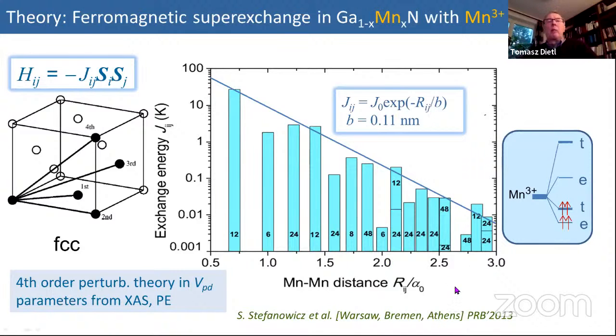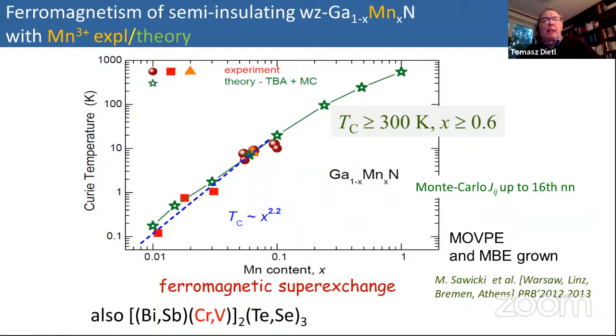And we can plot theory as a function of distance, and use Monte Carlo. We have been using Monte Carlo, having this interaction energy as a function of distance, to calculate TC. Mean field approximation, as you know, does not work in the case of short-range interaction. So Monte Carlo has to be used. And well, we can get quite a good description.